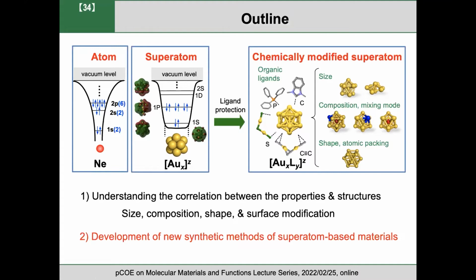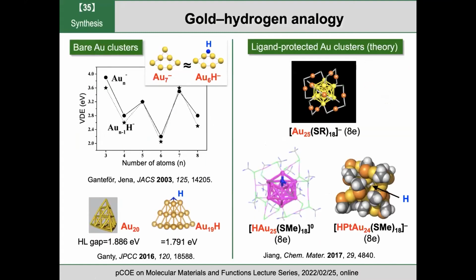Yield is not usually very high. Typically we can get a few milligrams of some clusters. So low yield is a challenge. In order to overcome these difficulties, we are now trying to develop transformation reactions. Okay, transformation from some clusters to another cluster with high yield or high efficiency. So this is what we are going to do.